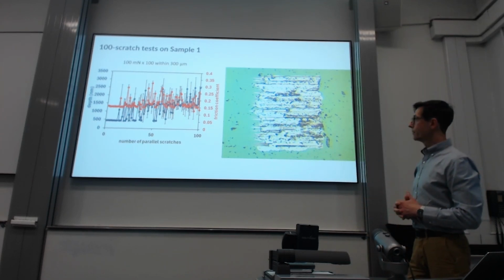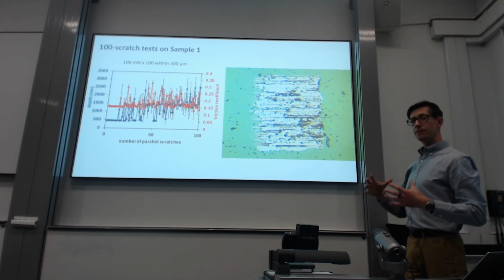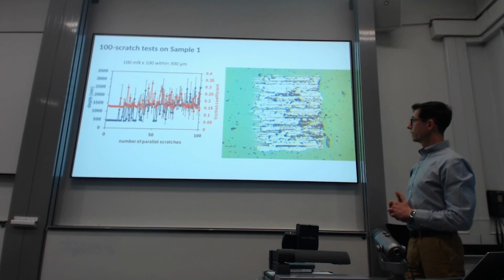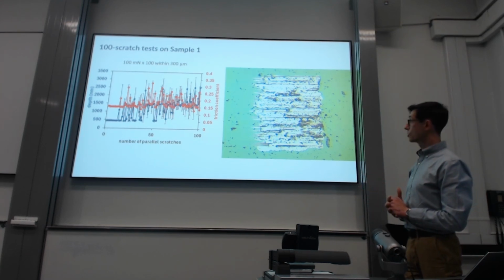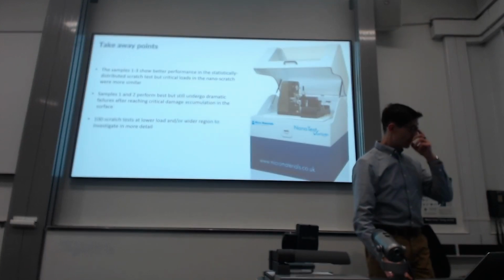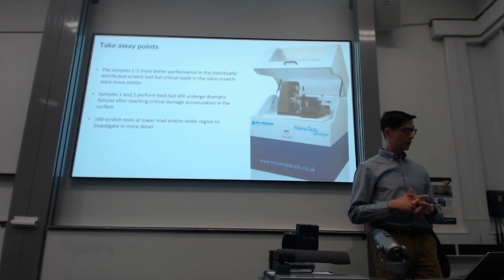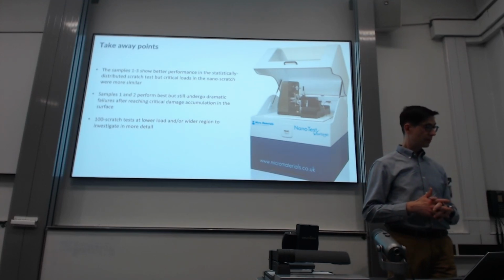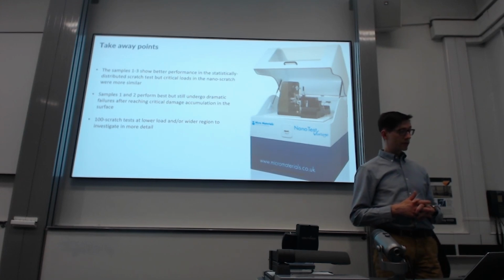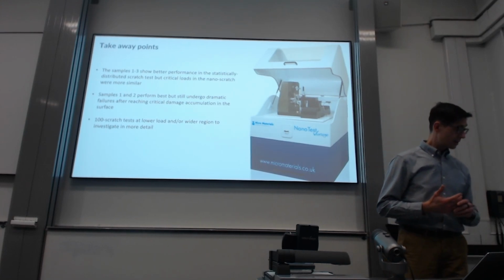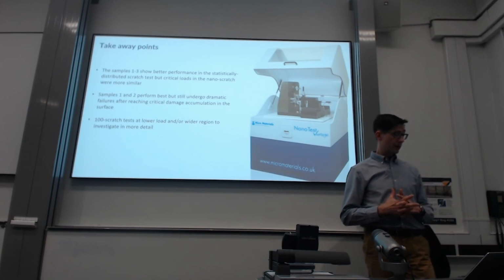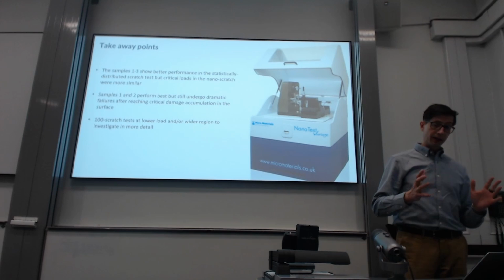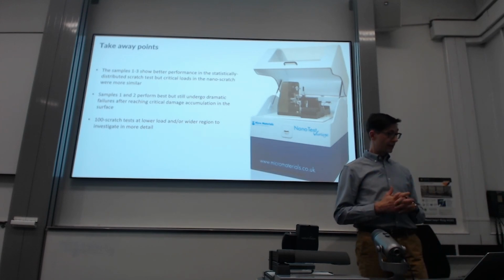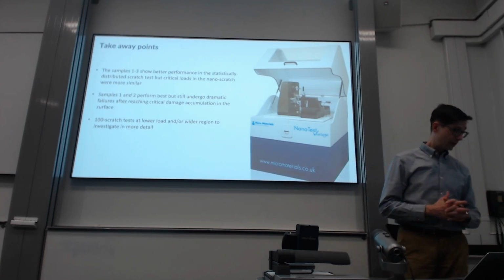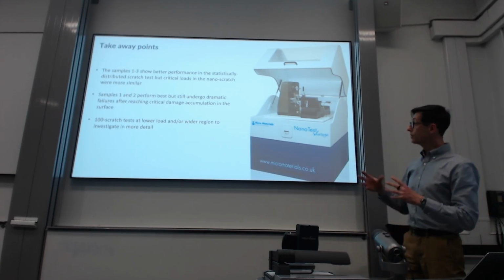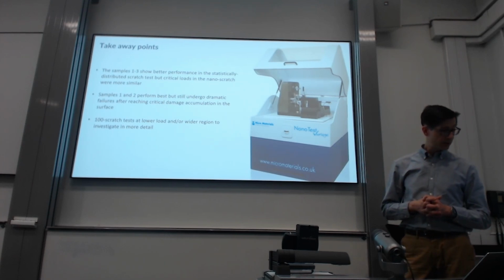So very useful method, I would say. There is a lot you can tune in terms of the area you cover and the loads you apply to characterize not only coatings but surfaces in general. A few takeaway points from that part. Samples 1 to 3, which were vacuum annealed samples, showed better performance in this type of experiment, but critical loads in nanoscratch were more similar. Samples 1 and 2 specifically performed best, but still undergo dramatic failures after reaching critical damage accumulation. And the 100 scratch test, which I liked so much, at lower load or wider region, was very useful to investigate the behavior of those coatings in more detail.